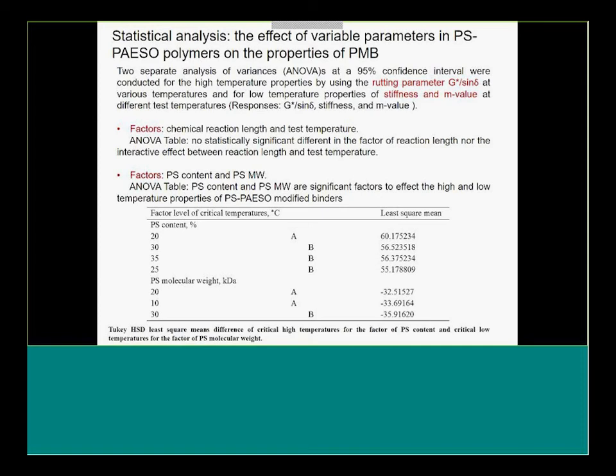Oh yeah. How many people in the industry are aware of this? I bet almost none, other than the polymer science folks that have studied this in detail in asphalt. Okay. However, we do see that the polystyrene on the low-temperature end does tend to provide a little bit better performance on the low end. It's about a 2, maybe 3 degree improvement on the low end, but it's about a 4 to 5 degree improvement on the high end.